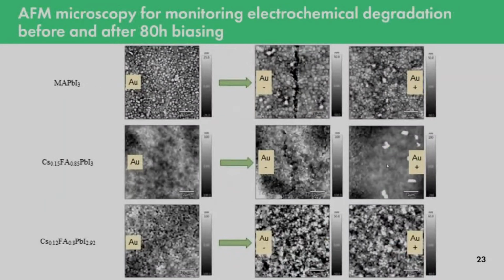So we also decided to check atomic force microscopy for this kind of film, and you can see here, once again for methylammonium lead iodide, the formation of a canyon along the cathode, strong degradation of the material. And for cesium formamidinium lead iodide, which demonstrated the best performance in previous experiments, there is also, but much less, formation of some kind of canyon. And you can also see that on top of the gold anode there is formation of some new species. Probably it's a reaction of gold with molecular iodine and formation of gold iodide, most likely according to the form and conditions.